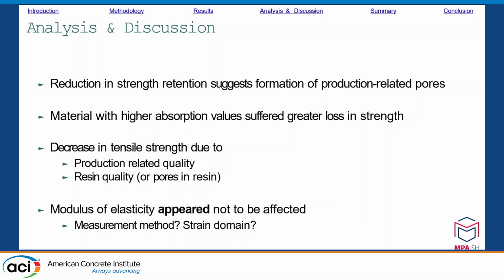The modulus of elasticity shows no change across all tests between rods with and without frost stress. This is rather due to the fact that the modulus of elasticity was measured by the extensometer at the outer edge of the bars and the damage occurred inside the bars.